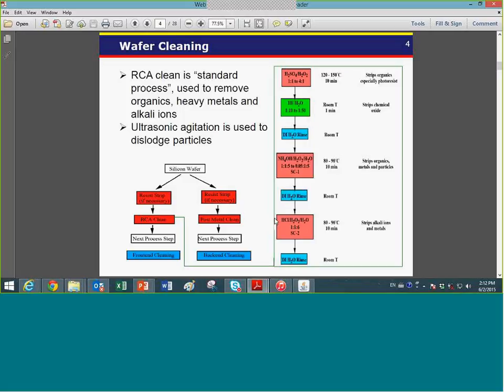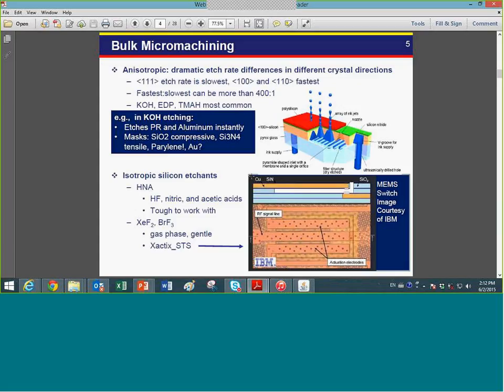The first step to start your fabrication is the wafer cleaning steps. There are typically two types of cleaning. One is for the silicon, where the RCA three-step cleaning is the most important step to start any process during the fabrication. Before any high temperature process, you must go through the RCA three-step cleaning. The second cleaning is after the bulk process on silicon. Usually it involves low temperature processes, so you just use solvent-based cleaning steps.